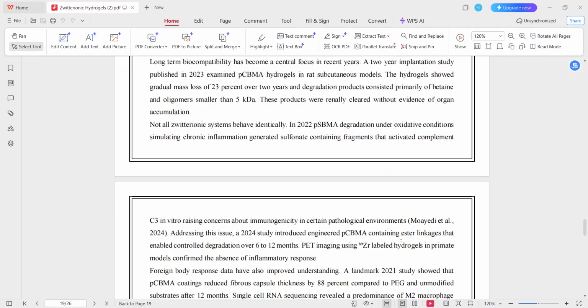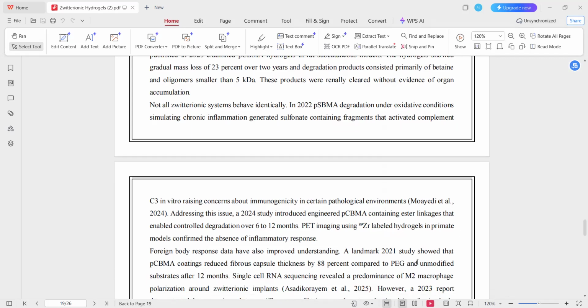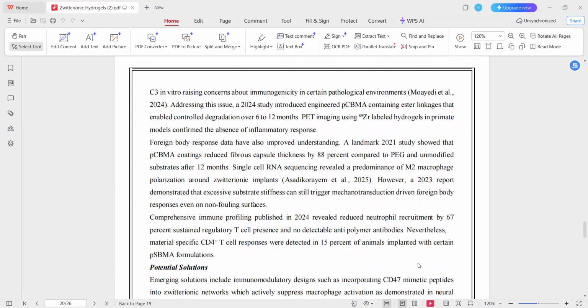In 2022, studies showed that sulfobetaine methacrylate (pSBMA) degradation under oxidative conditions produced sulfonate-containing fragments that activated complement protein C3 in vitro, raising concerns about immunogenicity under chronic inflammatory conditions. To address this, a 2024 study introduced engineered carboxybetaine methacrylate (pCBMA) hydrogels with degradable linkages that enabled controlled degradation over 6 to 12 months. PET imaging in primate models confirmed the absence of inflammatory responses.